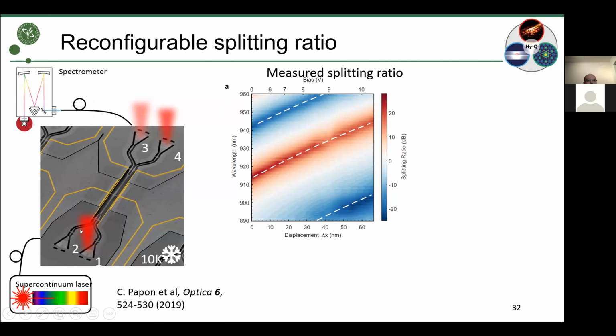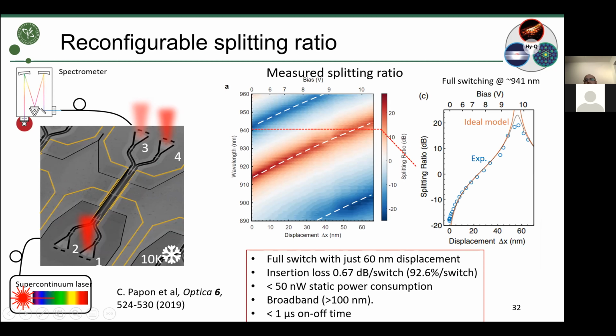So these are some of the experimental results. They're exciting. For example, one input port here, light travels through this, and then we are measuring the ratio of intensity at the output. So we're measuring the splitting ratio of this beam splitter. You can see that it fluctuates between minus 20 dB to plus 20 dB. So that's the full extinction of the device. And this is tunable as a function of the voltage that we apply. So the larger the voltage, the more we are changing this displacement. You can actually see from a cross section here that we're able to fully switch this device from one state to another with just about 60 nanometer displacement. So very, very tiny motion, very low loss and very low power consumption.